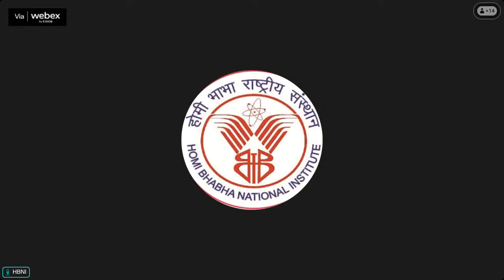That is because, if the source, the sample and the detector are on a fixed circle, and the sample moves by theta, the detector moves again by theta. So in total there is a 2theta movement from the incident ray. From the sample to the detector, that angle will be theta. But with respect to the incident beam, if it is completely transmitted through the sample, then that will again make a theta angle. So this theta and this theta, we take as the 2theta value.